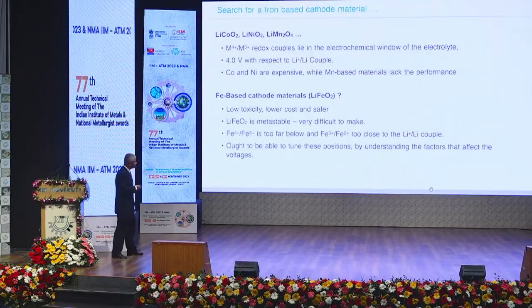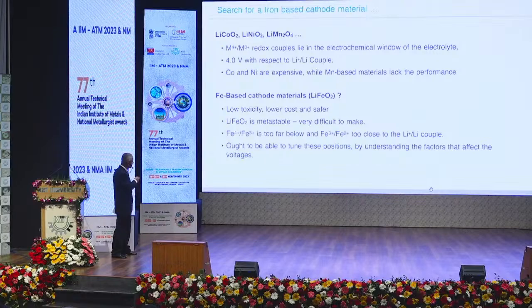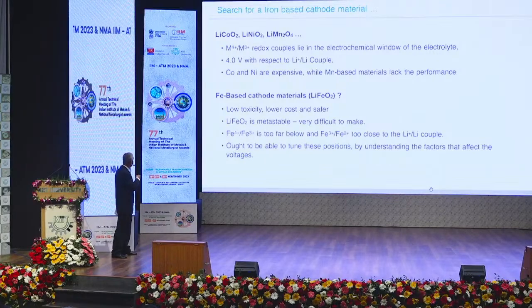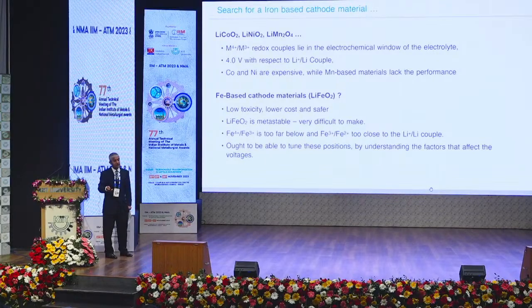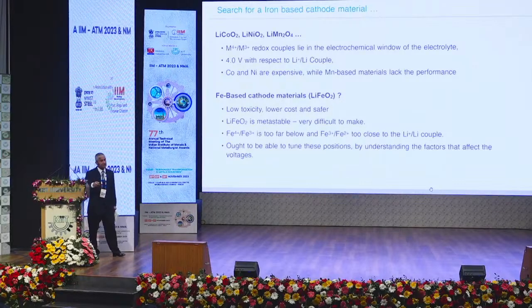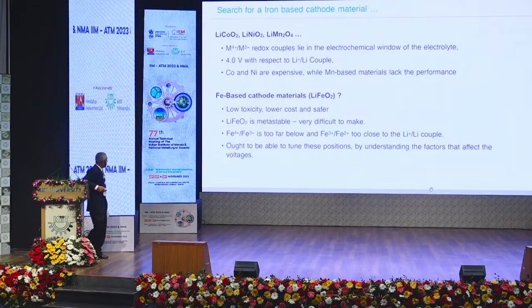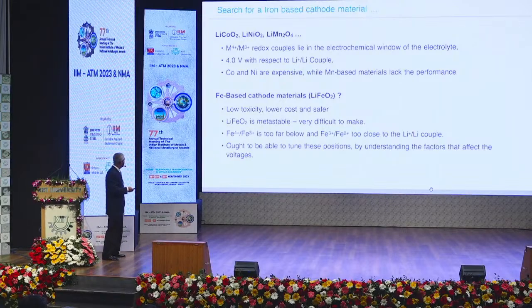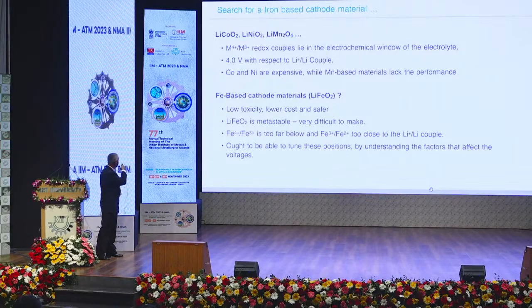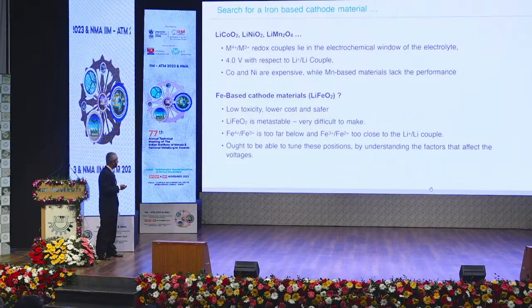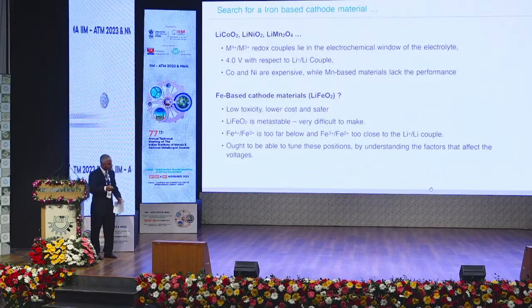So to summarize at that point, we have lithium cobalt oxide, lithium nickel oxide, and lithium manganese oxide, all of which are 4-volt batteries. But cobalt and nickel are expensive, while manganese-based materials lack performance. So there is always a need for iron-based materials because of lower toxicity, lower cost, and being safer. However, LiFeO2, which is analogous to LiCoO2, is very metastable and very difficult to make.